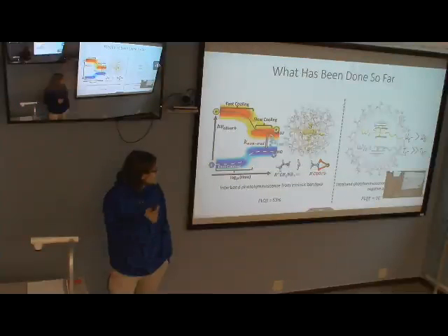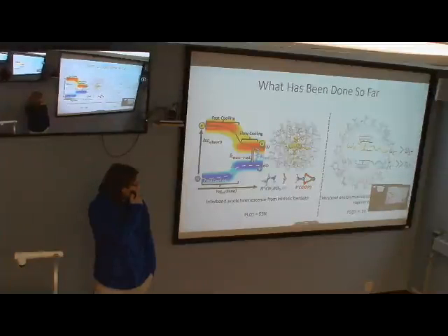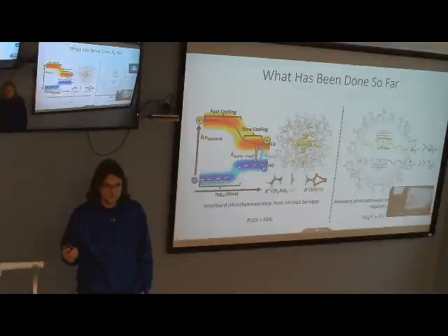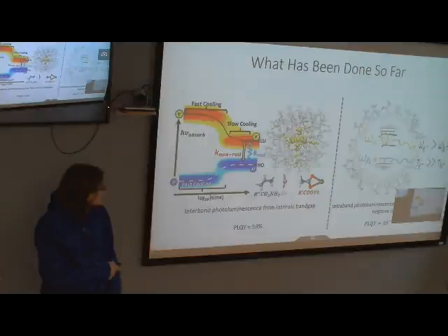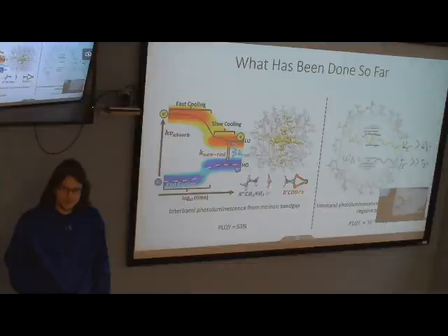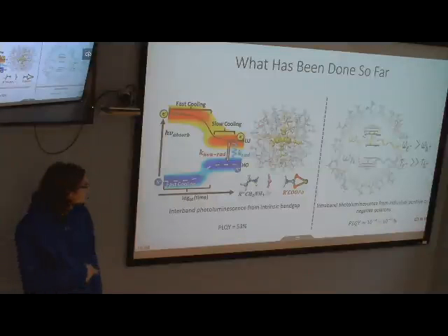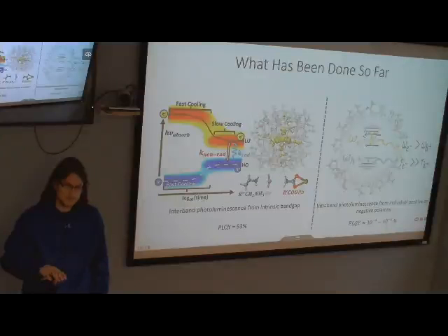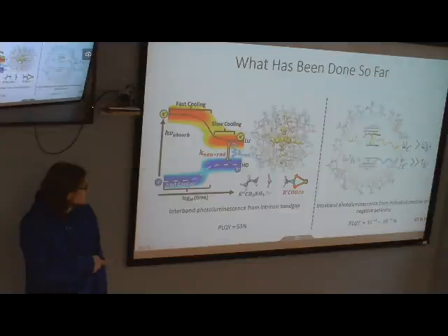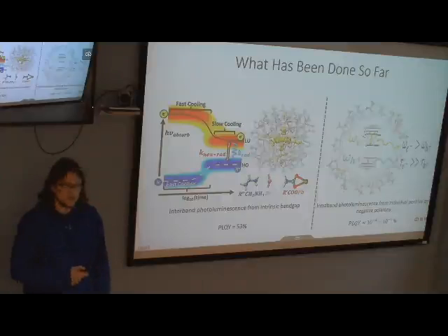So we explicitly accounted for adding either an electron or a hole into the system. That's what these pictures show: you put in a charge, either add an electron or remove an electron, and do the same dynamics, essentially the same calculations. And the provocative idea that we had for this model was modeling polaron photoluminescence. If you had a hot polaron, if you somehow could give it excess energy within the polaron potential well, and got a population inversion of your polaron, whether you can get photoluminescence from that.